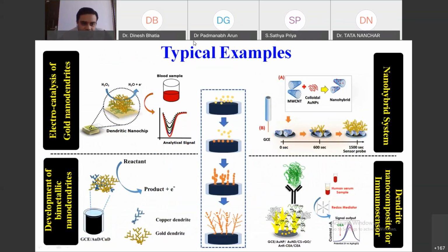In the first one, we have developed 3-dimensional nanostructures onto the surface of the indium tin oxide electrode or chip, the dendritic chip, and it has been utilized to detect hydrogen peroxide in the blood sample directly. Second, we have developed a nanohybrid system. This nanohybrid system was serving as a surface for the development of the 3-dimensional nanostructure again.